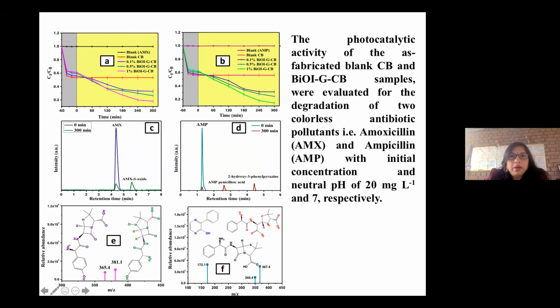Now, these are the photocatalytic activity results. This is the blank one. When you see the blank ampicillin, nothing is happening, but carbon block, yes, it shows adsorption completely, but not photocatalytic degradation. But when the material was immobilized, it shows adsorption as well as degradation. The 1% BiOI G carbon block, with 0.5% different quantities of the material immobilized, was compared, and 1% gave the best result among all. So these are the results. Amoxicillin was converted to amoxicillin N-oxide, and ampicillin was converted to penicilloic acid and 2-hydroxy-3-phenylpyrazine.